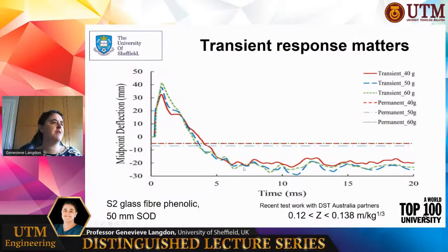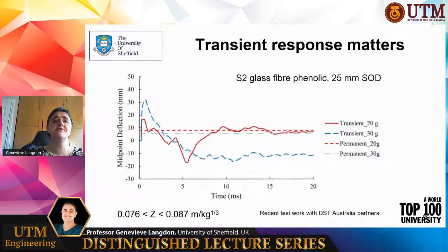By the time you get to about 6 or 7 milliseconds, you have deformed in the opposite direction to the explosion, which is a very interesting thing. What this means is that the transient displacements are much larger than the permanent response. You can also get very high peak negative displacements in the opposite direction to the explosion. The reason for that is something called reverse snap buckling, which is a feature in materials with high elasticity and is the reason why looking at transient response in a fiber reinforced polymer is so important, because the transient displacements can be up to 10 times, maybe even more, the permanent response.